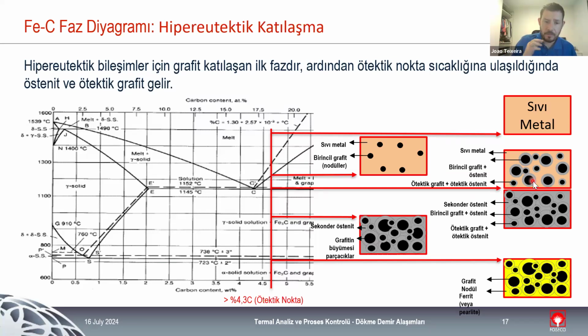So we always have to pay a lot of attention to the type of solidification that we have. And this is one of the main reasons. So we have a lot of graphite being formed at early stages, really big ones, really big nodules if you are talking about nodular cast iron. So we have a really quick expansion. And when we reach the eutectic level, we still have some carbon in the melt. We still have some nodules that are going to form, but they are smaller. So we have less expansion.